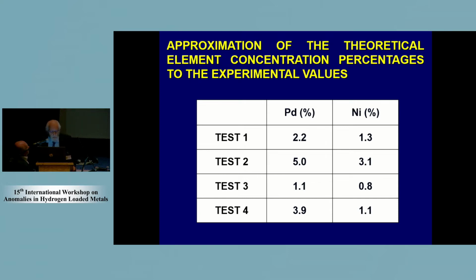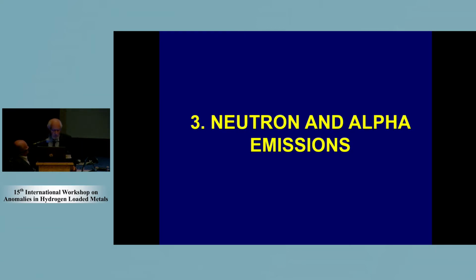You see the values that we had for palladium are 2.2, 5, 1.1, and the last is 3.9. Then you see that for the nickel, that I've not commented up to now, we had very small deviations. In some way, they are only a fraction of the previous one, between 1/3 and 1/2. Very small, but I have not the time to go to the details for nickel, but also for nickel we have the same kind of analysis.